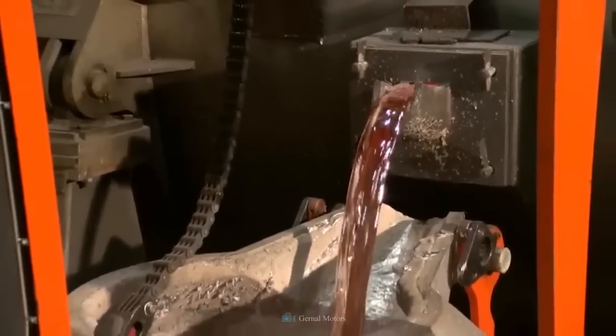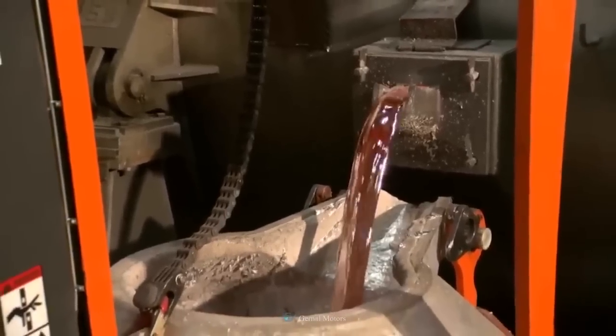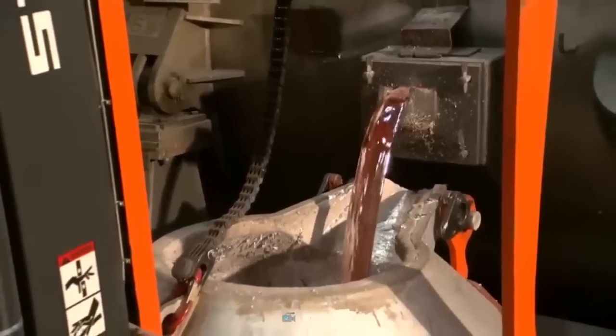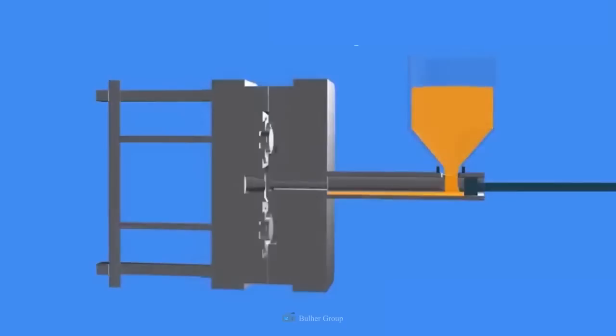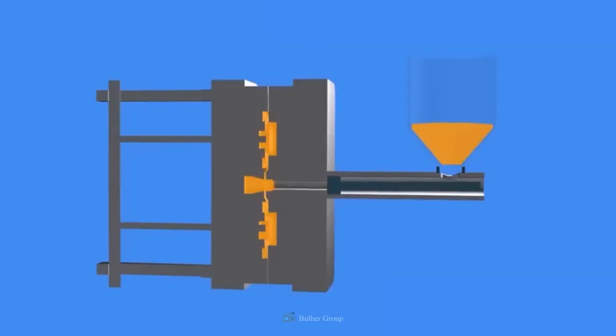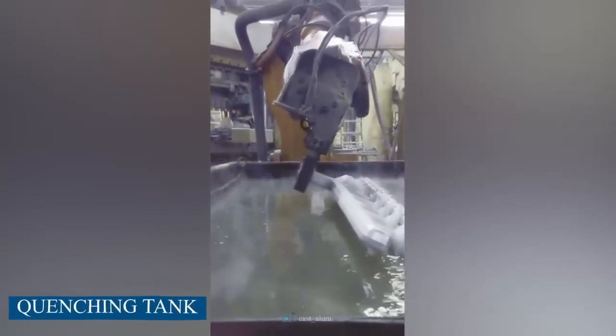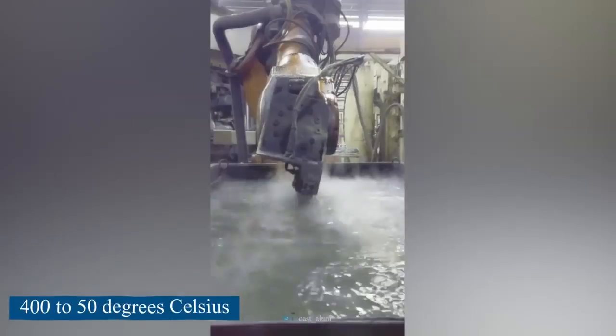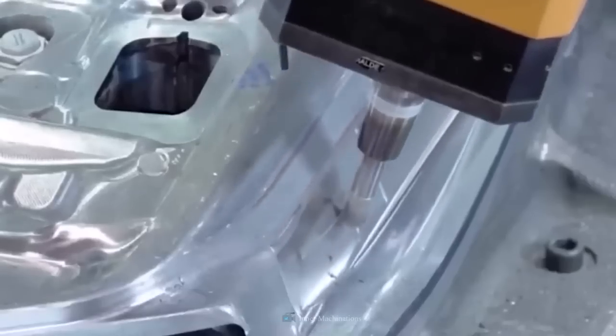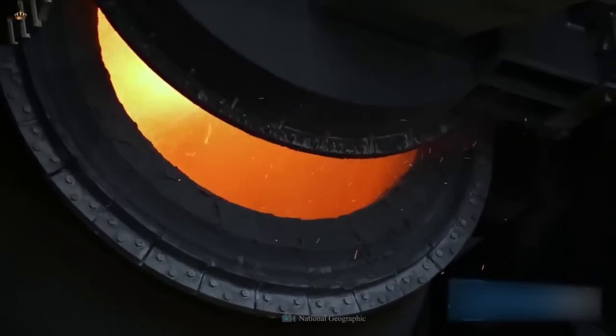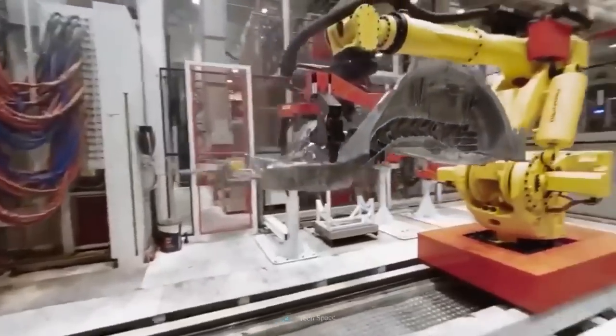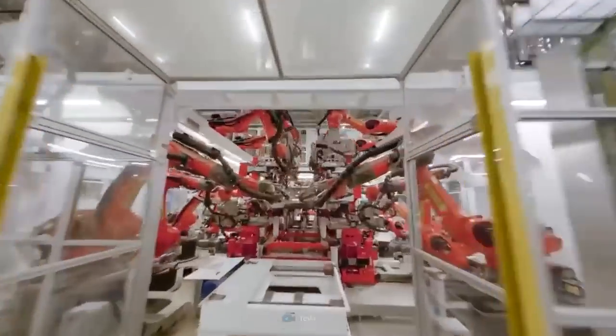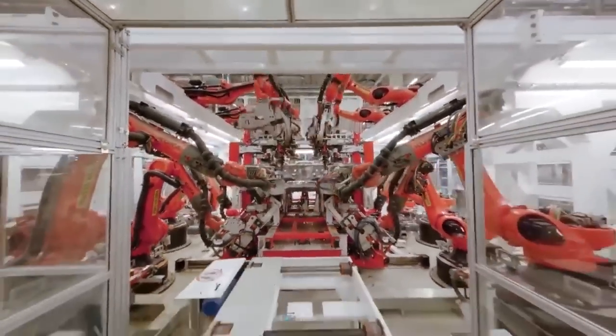A precise amount of molten metal is pushed from the holding oven into the casting chamber of the Gigapress at 750 degrees Celsius, and is then pressed into the mold using a high-speed plunger and 8 milliliters of extra lubrication. At 400 degrees Celsius, the mold is broken and the raw casting is extracted. A robot removes the casting and places it in a quenching tank to lower its temperature from 400 to 50 degrees Celsius. The approximate margins are trimmed using a mechanical trim press, and extra aluminum is recycled back into the melting oven. The remaining serviceable portion of the casting is X-rayed to examine the internal structure, laser trimmed, drilled for fittings, and computer measured for precision.